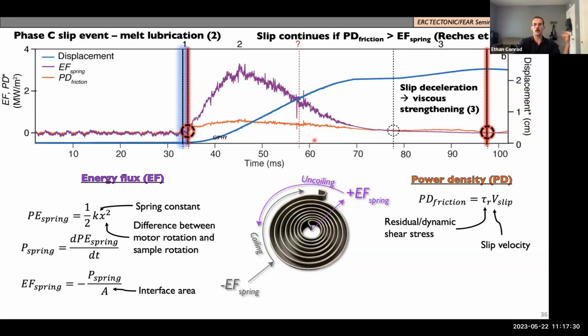Okay, so when these cross, you would lead to slip deceleration and viscous strengthening. And so we see what was stated by Reches: when you change over, you start to enter this arrest phase, and things start to come to an end, and you start to slow down, and then ultimately you get to arrest. And I like to think about this like a burnout in a car.